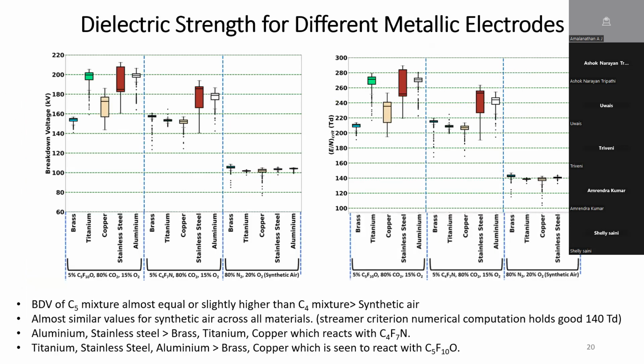Over here, on the left-hand side you see the breakdown voltages, and on the right-hand side the E/N critical values. The first five correspond to the five materials in C5. The next five are the materials in C4, and the next are the materials in synthetic air or technical air, 80% N2 and 20% O2. As you can see, air is obviously much lower than these two, which we also said in the previous one, and there's a lot of literature on that. But what we see is the breakdown voltage of C5 mixture is almost equal to or slightly higher than C4, which is also expected, and that is much higher than synthetic air.